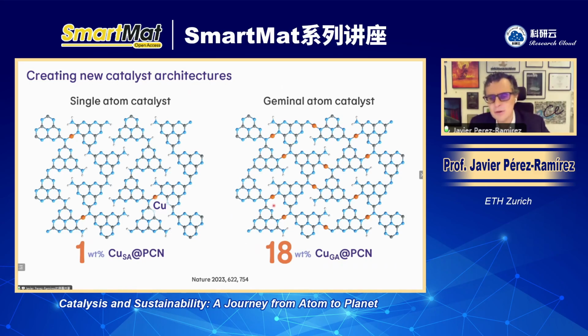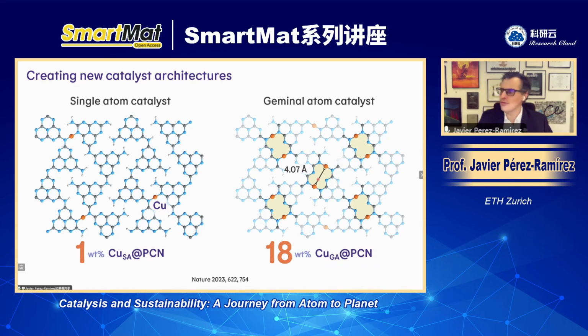And the very unique aspect of this catalyst is that now the copper atoms are still isolated, but they are twins. And actually they are very close to each other, about 4.07 angstrom. And this class of materials is actually enabled by two aspects. Number one, our host has a crystalline structure, so we know where we are placing the metal. Two, we are able to produce high density. We are able to increase the metal loading to catalyze this proximity of the metals. This is what we call a geminal atom catalyst. And this is what we call a geminal site.